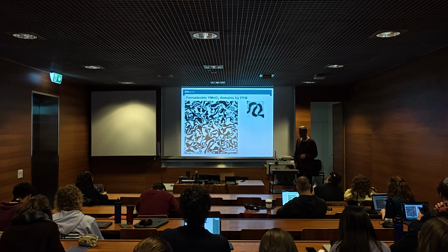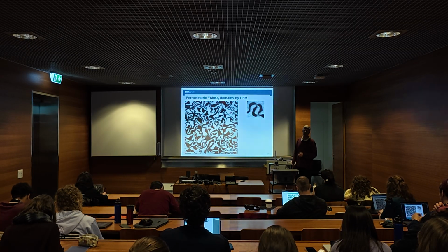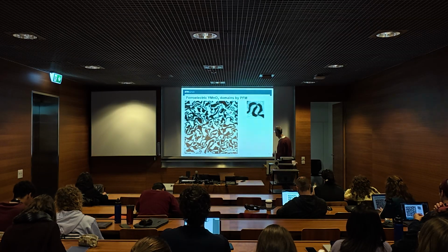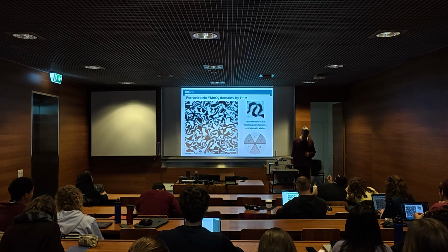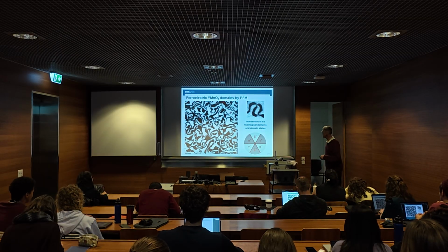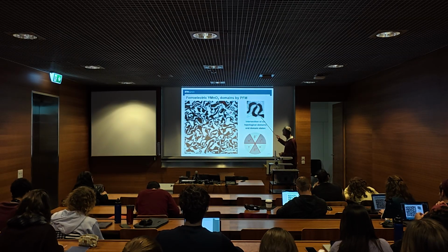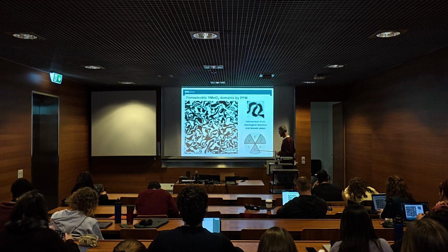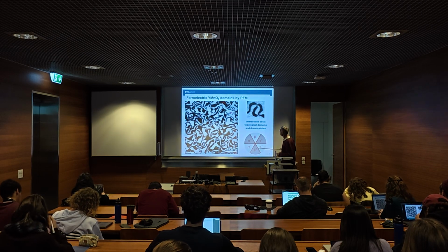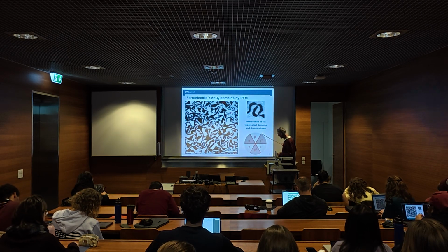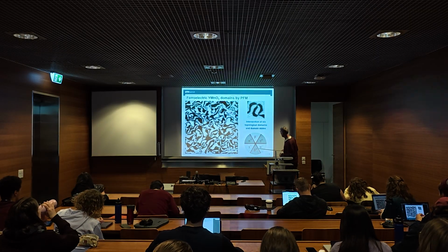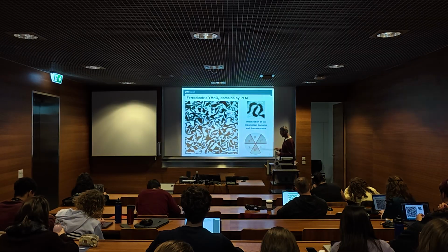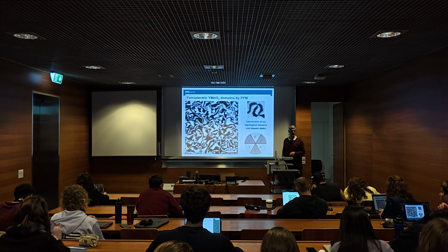There are reasons for that, mathematical reasons. So this is a topologically created domain pattern. The reason is that domains are not only ferroelectric domains, they're also elastic domains, so distortive domains. Here the ferroelectricity is improper. What it primarily is, is deformed in some form, and then in 6 different ways, so 6 distortive domain states, and 3 of them are plus polarized and 3 of them are minus polarized, improperly ferroelectric.